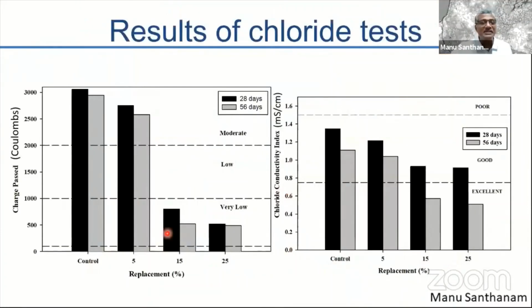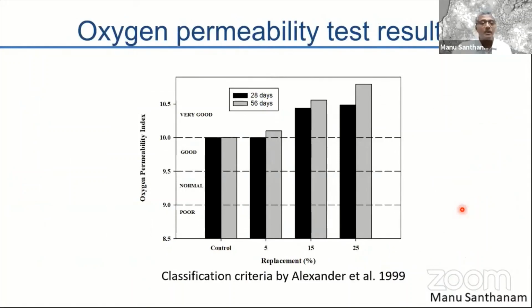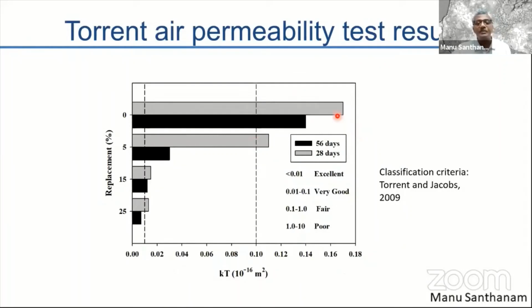Right, so here you can see the results of chloride tests. The RCPT you can see significantly lowered when you have normal replacement levels of bagasse ash. Here, chloride conductivity index with the South African method again produces much better quality of concrete with bagasse rather than with plain Portland cement. Again, oxygen permeability index is enhanced with the use of bagasse ash replacement. And of course, you can also see the air permeability as per the Torrent measurement. You can see the permeability index is reduced significantly as compared to plain Portland cement.